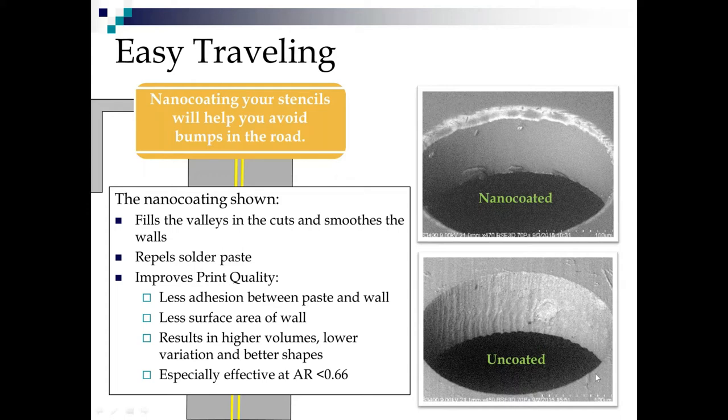But these pictures, because they're blown up so much, look a little grainy. These are SEMs of stencil apertures that have been laser cut. You can see the striations around the top surface where the laser penetrated, and then hot air blows the molten metal away. So when you see those striations get a little more random near the bottom, that is actually from turbulence from the air as it's blowing it through. Anyway, this is a really, really good cut that we're showing here, and it's still got valleys and hills in